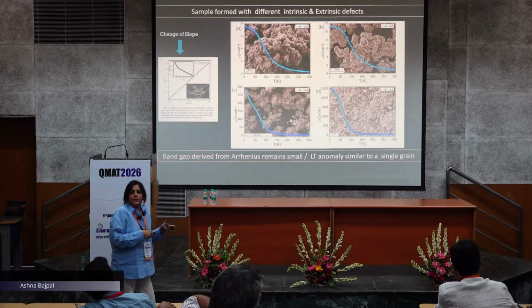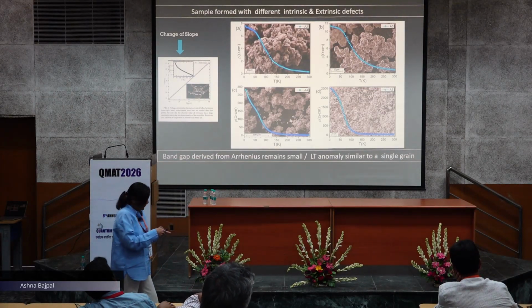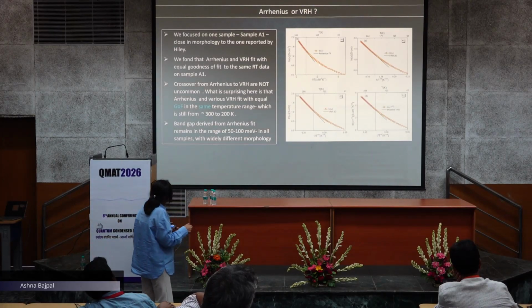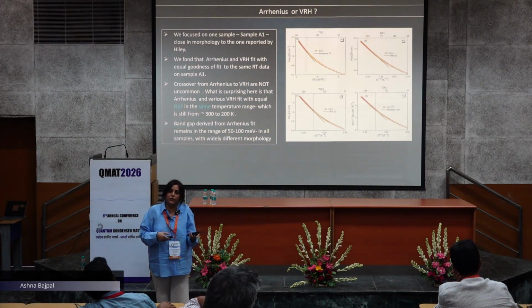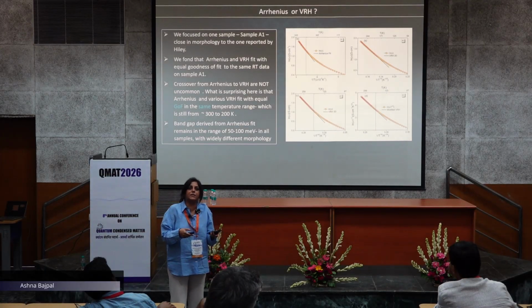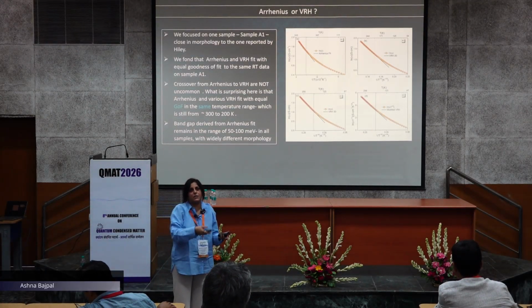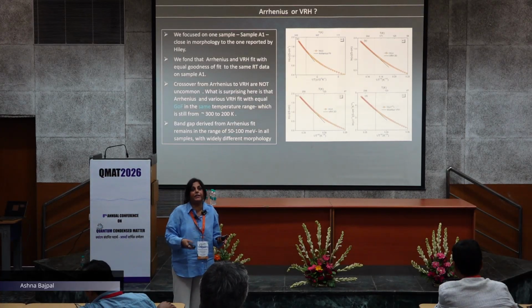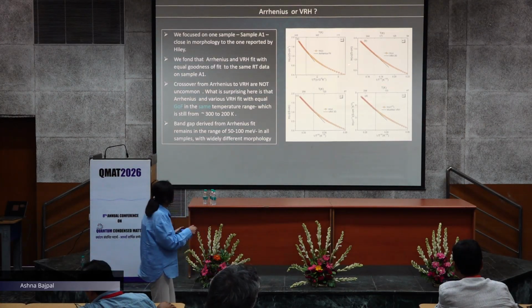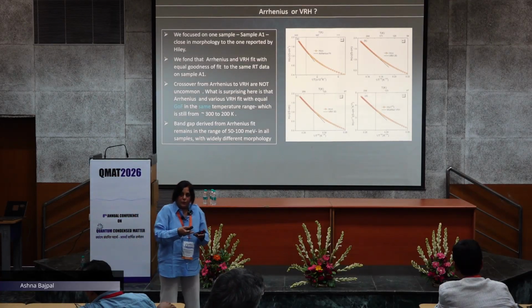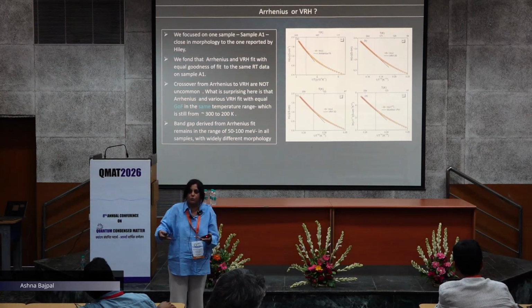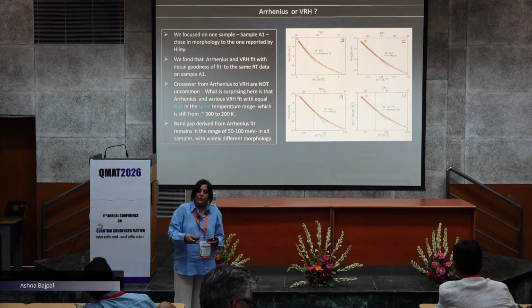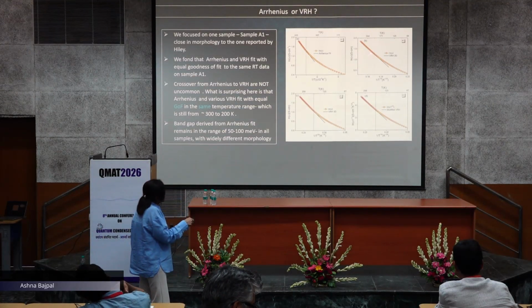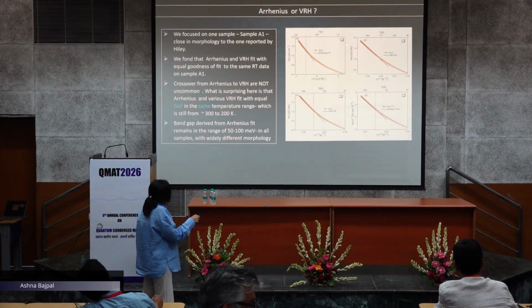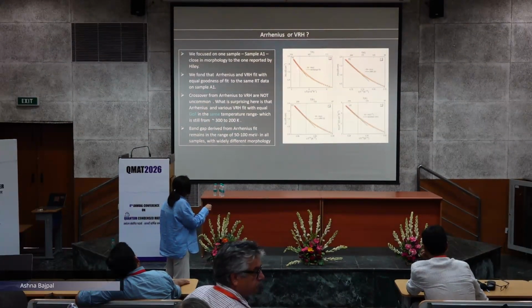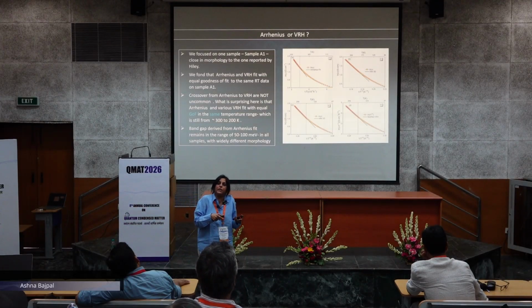And the second is, what is the conduction mechanism in the low temperature region? Those who work in the field of oxides know that the variable range hopping mechanism is the second best thing after Arrhenius, if you have this semiconducting type of behavior or activated transport. So we tried variable range hopping. Since conduction is limited to the RuO2 planes, we tried 2D and 3D, and we found that Arrhenius as well as VRH or modified VRH all fit very well in the high temperature, with equal goodness of fit.